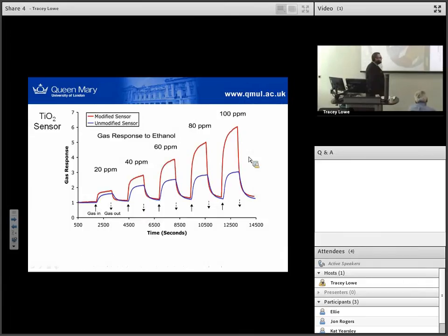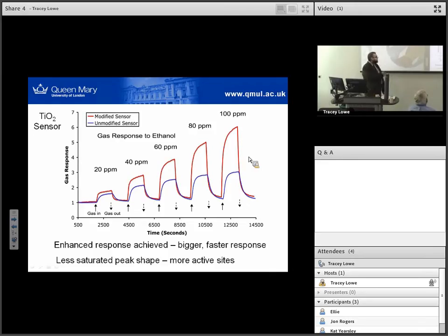But for some of them, if we look at the gas response to ethanol, you can see for our modified sensor, shown as the red trace, we get a bigger gas response. We tend to get less saturation on our peaks, indicating more active sites. So we produced an ethanol sensor that's a little more responsive than what we can normally achieve.